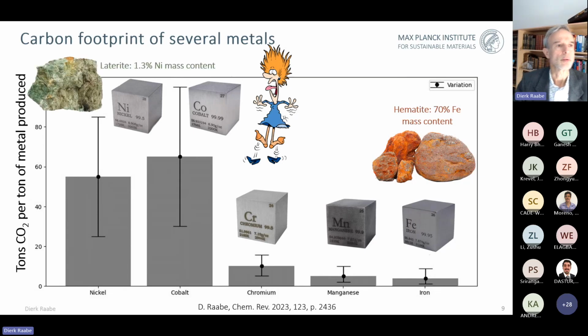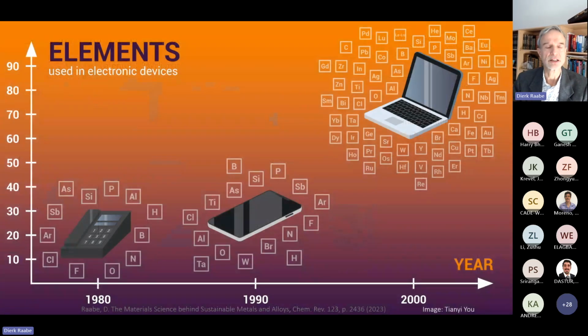When we go to materials like nickel or cobalt or also copper, very similar, then these best available commercial ores that are industrially used have a very low metal content. Look here, a laterite, which is a typical weathering oxide used for nickel extraction, has probably 1.3% nickel only. That means you are permanently heating and enriching material that does not contain much of what you are seeking. So that gives you only a glimpse of how complex these enrichment and extracting problems really are.